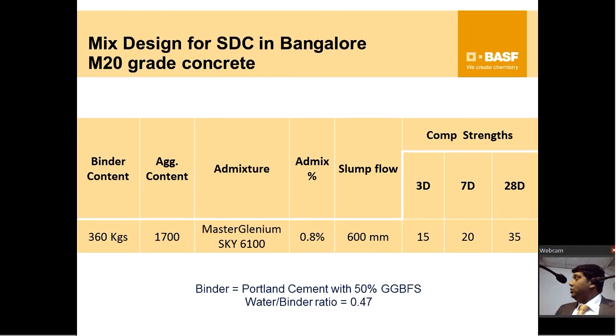Okay, so here is where the difference is, where you are able to show the lowest cementitious content possible that passes the V-funnel at 5 minutes, and all those other values. Let's go a little faster. Record after record, this is another record with 2.4 kilometer long pumping. This is for a Chuzachen hydropower project.